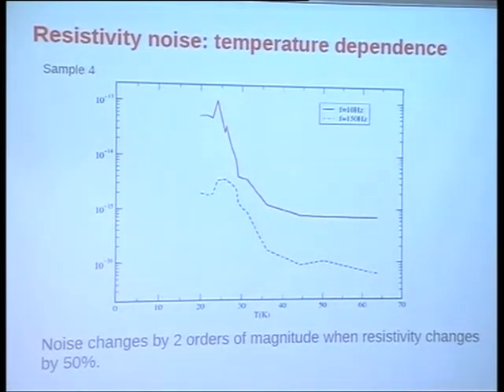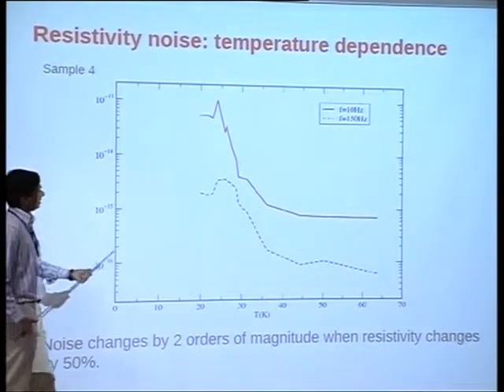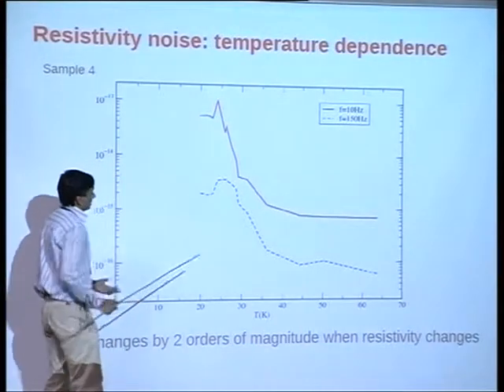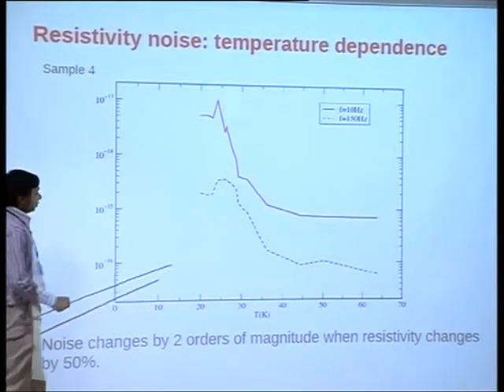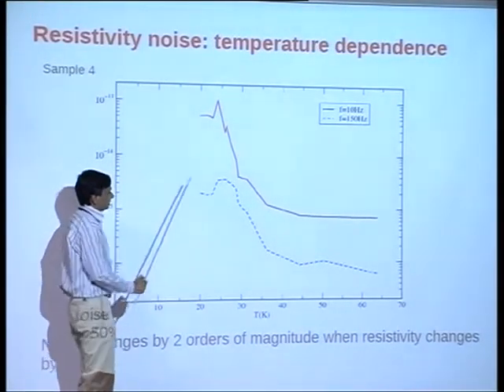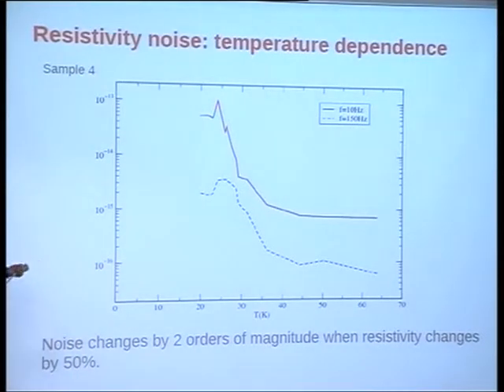Okay, here's the temperature dependence. This is much more noisy, and we really are not very successful, as you will see, with modeling these, but roughly they show the same characteristic features as the resistivity. The good thing about noise is that whenever resistivity has changed just by 50%, the noise manages to change by 2 orders of magnitude.